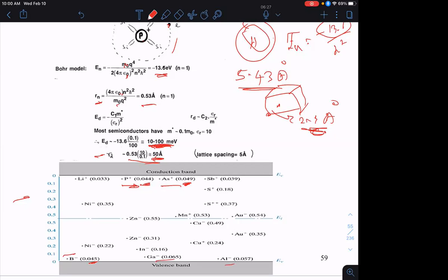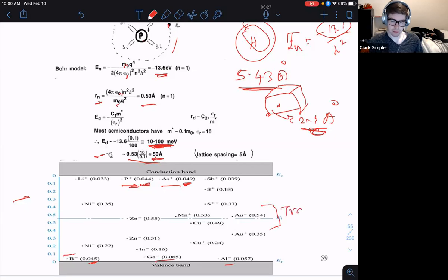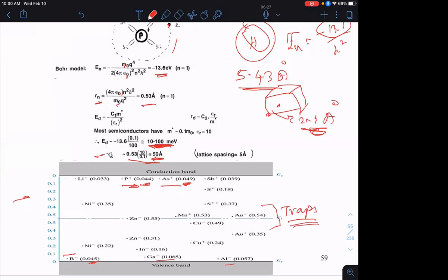On the other hand, if you introduce impurities such as gold into a silicon crystal, are these shallow or deep? They're deep, right? And therefore they act as electron or hole traps. So if you work at, say, Intel or Samsung and you accidentally introduce gold into the semiconductor factory, into the wafers, they'll take you out into the parking lot and shoot you on the spot.